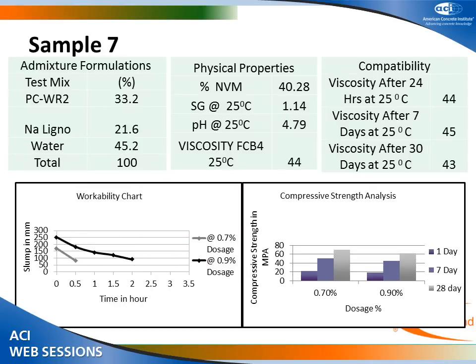Then we have tried another source of polycarboxylate, which is WR2, and this is again a 50-50 combination with the South African lignosulfonate. We can see that again the slump retention at 0.7 was not good, and compared to the first one was not up to the mark at all. Whereas at 0.9 it was slightly improved, but still not as good as the first combination. Compressive strength-wise, again it was good at 0.7, around 64-65, and at 0.9, 61-62.